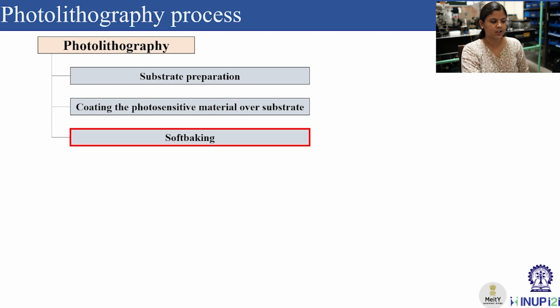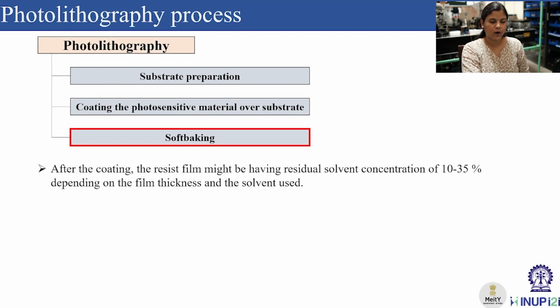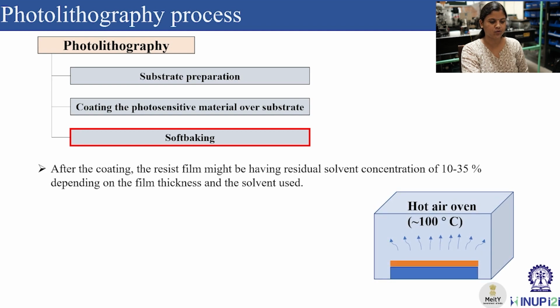The next process involved is soft baking. Why is this needed? After the coating, the resist film might have a residual solvent concentration of 10 to 35% depending on the film thickness and the solvent used. In order to get rid of this solvent, we heat the coated substrate at around 100 degrees Celsius either on the hot plate or in the hot air oven as shown here in the figure.